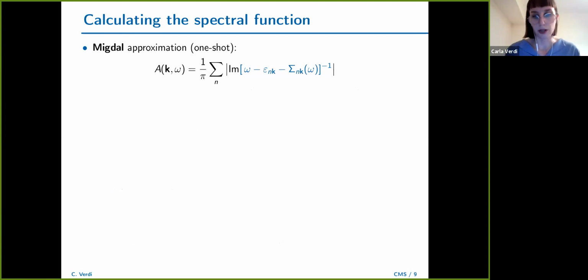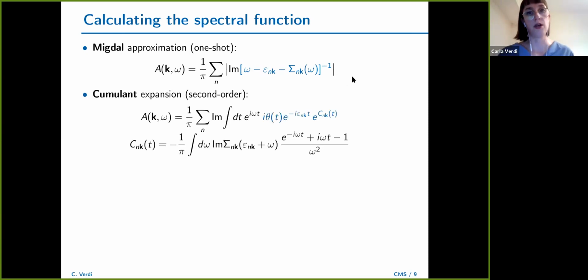In many-body perturbation theory, within the so-called Dyson equation, the spectral function is calculated from, as I said, the imaginary part of the Green's function. And it's this expression here called the Migdal approximation, which is basically what is called the Dyson equation. There is a better approximation that one can do, and it's called the Cumulant Expansion. I don't need to go into many details, but basically it means that you're including some additional diagrams that are not included in the first expression here in the Migdal approximation. So it is more accurate, and it still requires only the calculation of the self-energy that I showed you before.